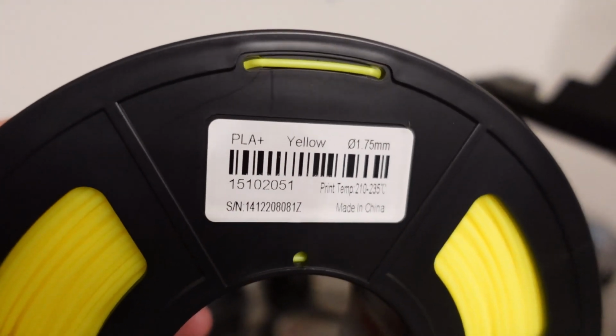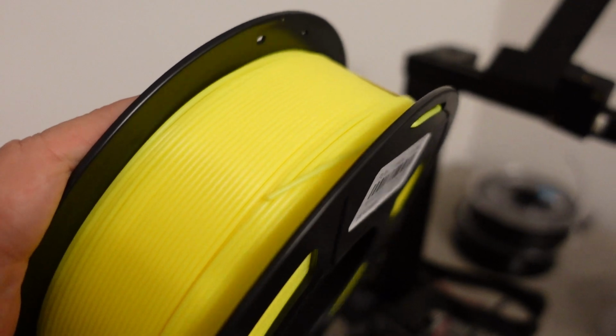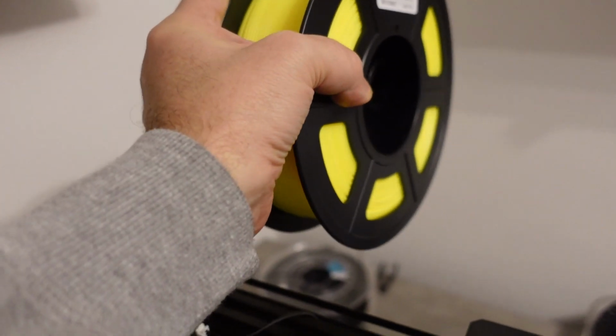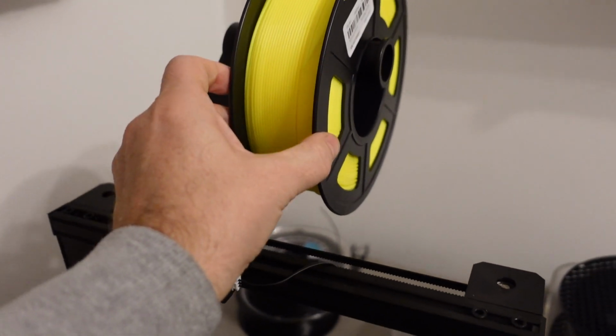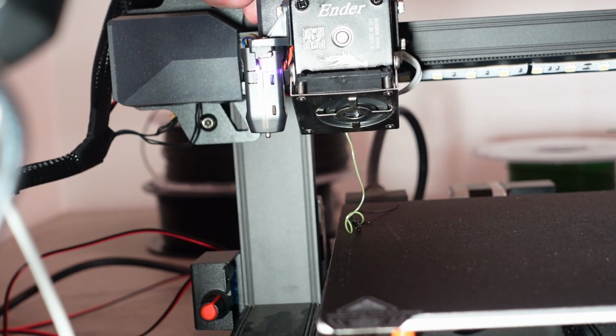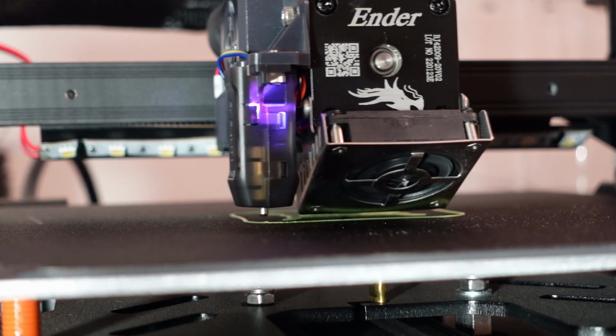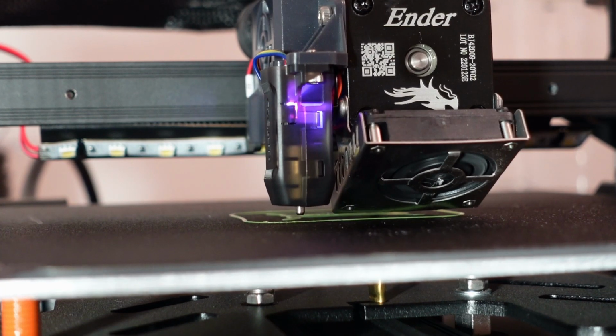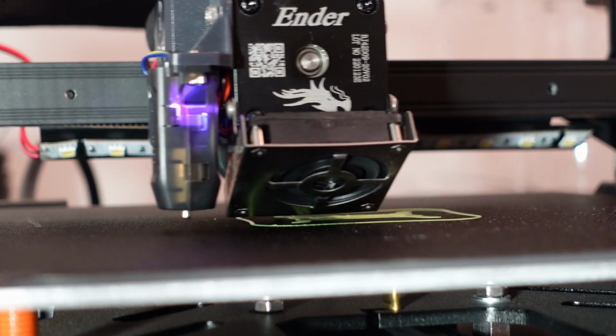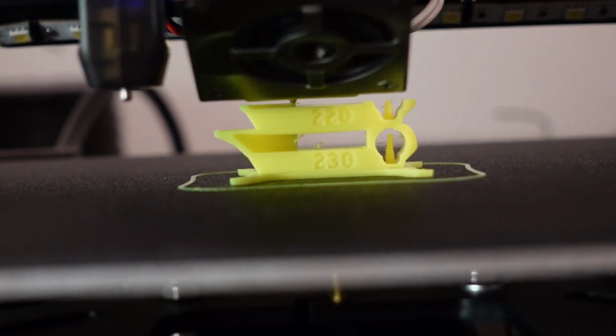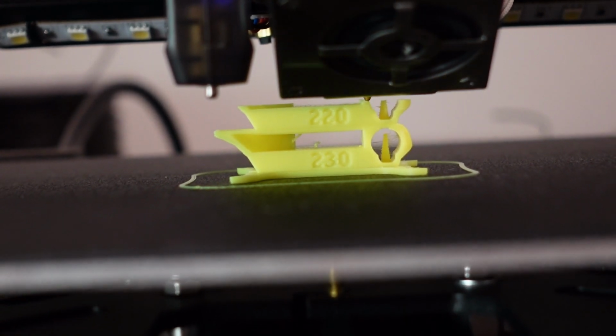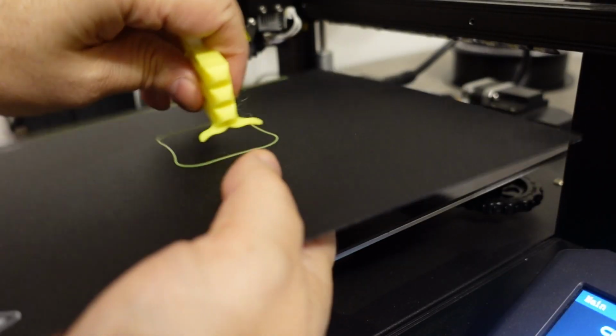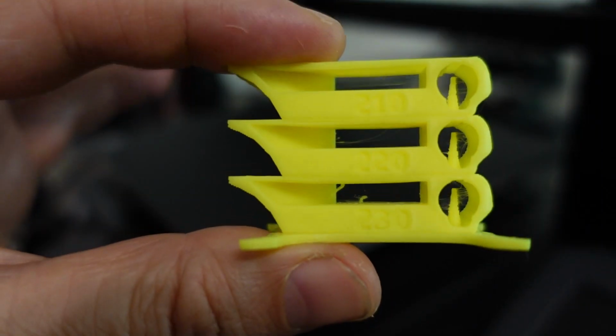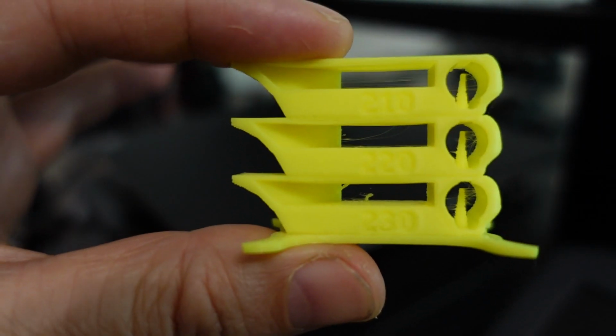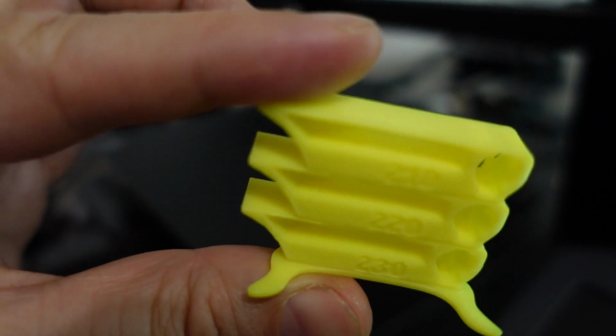And now PLA Plus, and this yellow color will be a real refreshment for this video, and the temperature tower will be from 230 down to 210 degrees Celsius. And like with other PLA filaments, there is no problem with the first layer or the bed adhesion. This will be another very clean printing. Just a few strings on maximal printing temperature, but otherwise this is another perfect temperature tower.